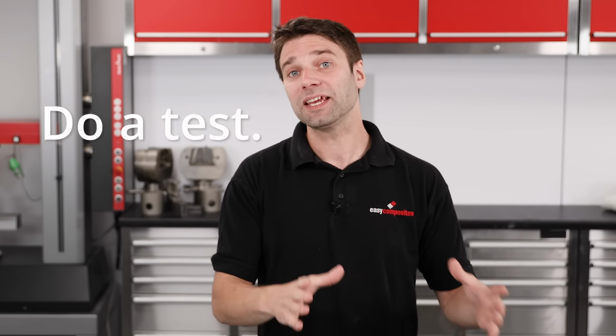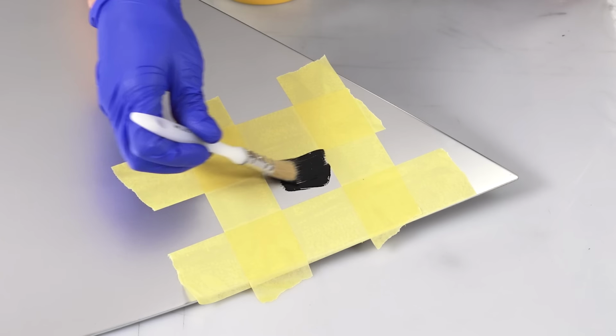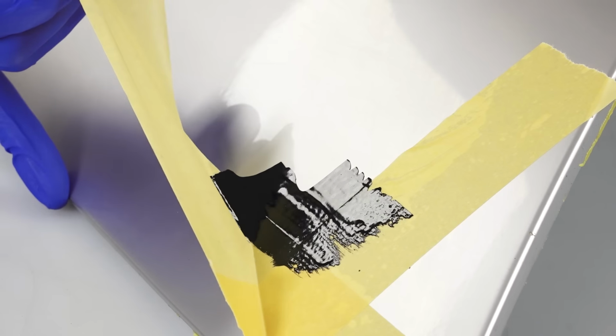On a final and important note on pattern materials, if you are in any doubt whatsoever as to the compatibility of the surface, maybe it's an unknown paint system or plastic or just a brand of 2K paint that you've not used before, do a test. Simply prepping and applying a small patch of gel and checking that it easily releases 6 hours later is going to tell you whether you're going to have any issues. And a small amount of patience at this point could save you the hours of time that have no doubt already been put into your pattern.